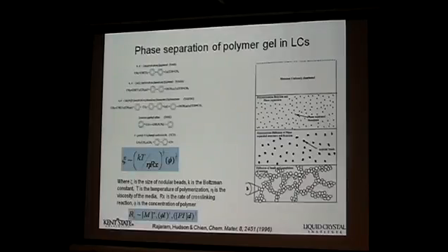But without that, by using a small amount of polymer, 2 to 3%, you suppress the cone angles, right? The polymer will form in between the layers, this layer, that layer. So when the molecules respond to the applied field, they try to tilt out of the plane, and then they get compressed by this polymer network. So that gives you the smectic A like switching. Something like that is very important, right?